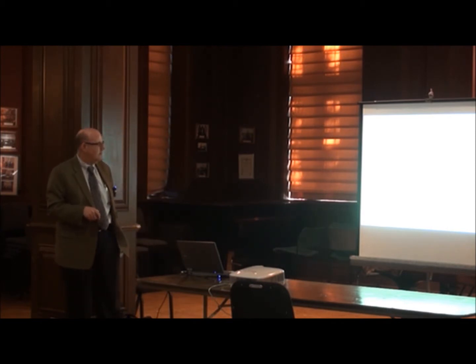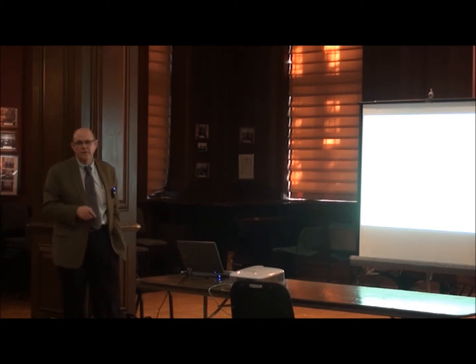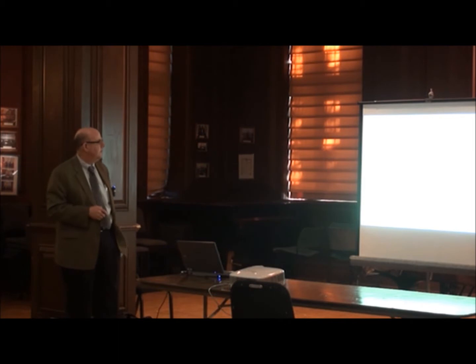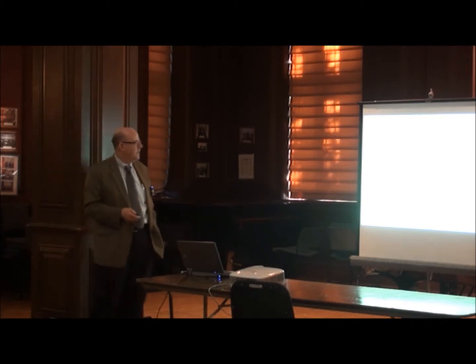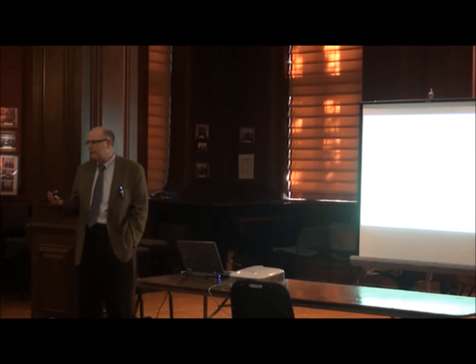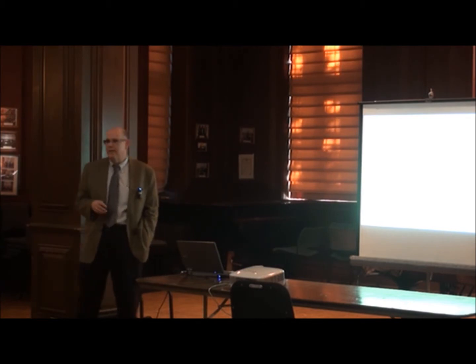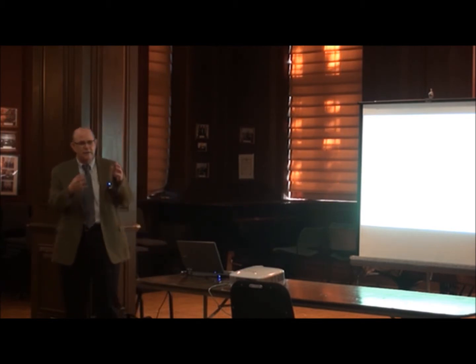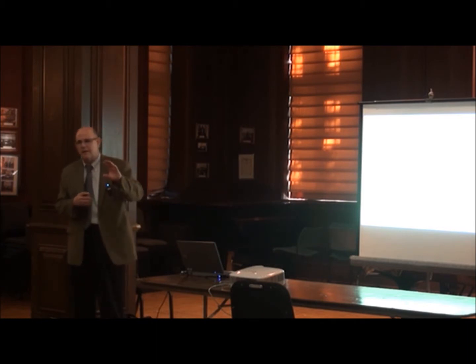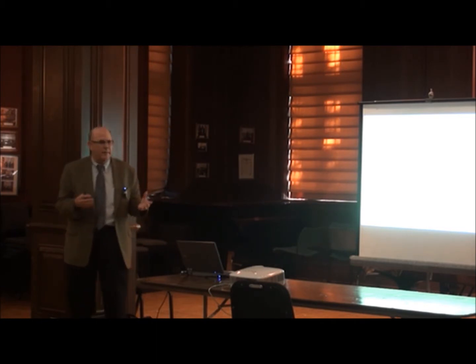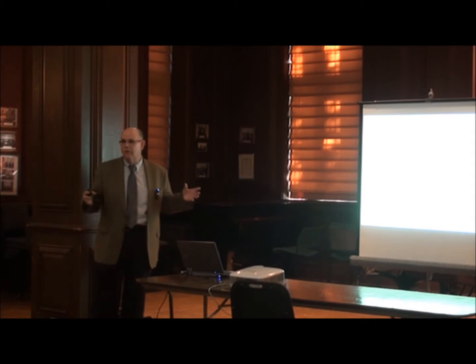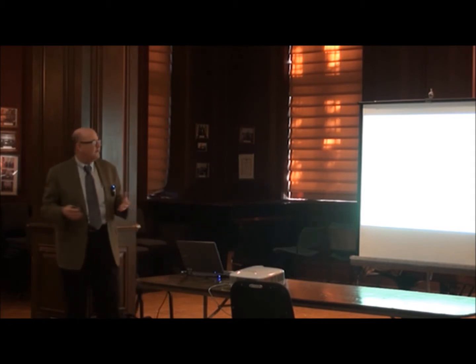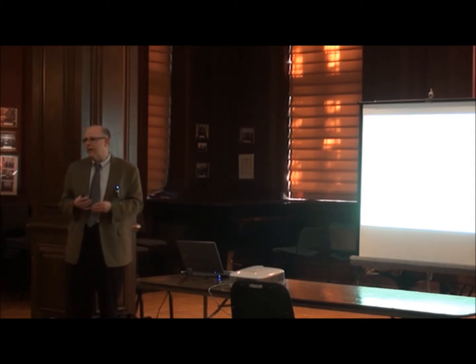Bhushan, who's one of the fundamental pioneers in this field, basically shows as a function of skewness how the real area of contact changes, and as a function of kurtosis how the real area of contact changes. So different parameters that we've been working with in surface metrology can also be related to the real area of contact. Where I developed along the school of thought of radius of curvature and average roughness, there's other papers that say we can look at just the autocorrelation on the surface or the slope on the surface and relate that to the real area of contact.